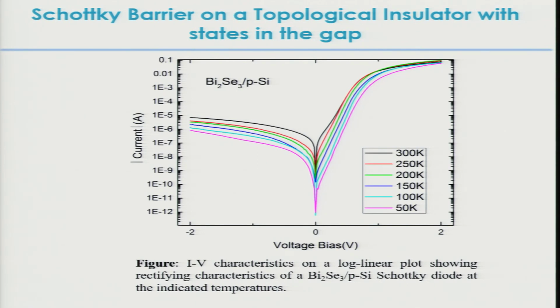This is where topological insulators come in. If we can look at CDWs and we can look at superconducting states, our theory was we could look at the topologically protected surface states. We made a junction on bismuth selenide, Bi2Se3, on silicon. Now, silicon you can't cool down below 50 because of carrier freeze out, but this is one of the most beautiful junctions that we've seen. The linearity here is about 6 decades in current.